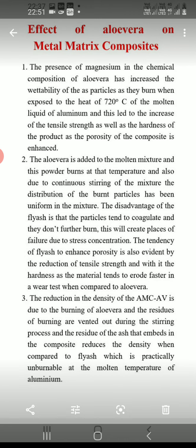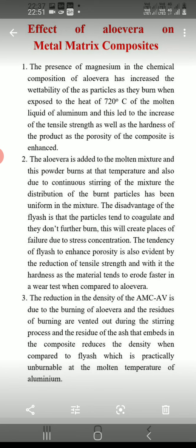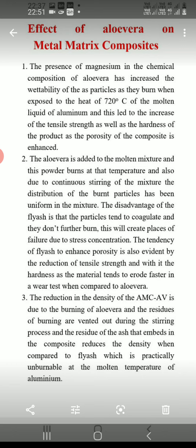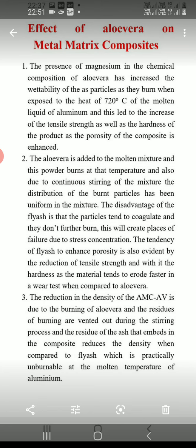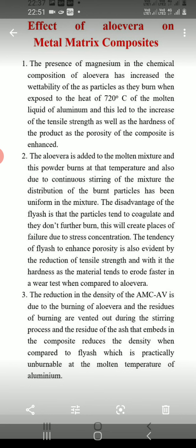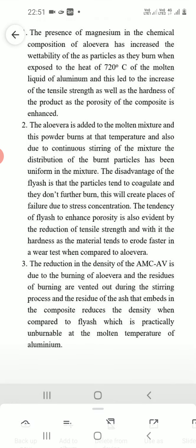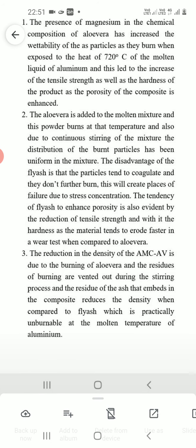Secondly, the aloe vera is added to the molten mixture, and this powder burns at that temperature. Also, due to continuous stirring of the mixture, the distribution of the burnt particles is uniform in the mixture. The disadvantage of fly ash is that the particles tend to coagulate and they don't burn further. This creates places of failure due to stress concentration. The tendency of fly ash to enhance porosity is also evident from the reduction of the tensile strength, and with it the hardness, as the material tends to erode faster in the wear test when compared to aloe vera.